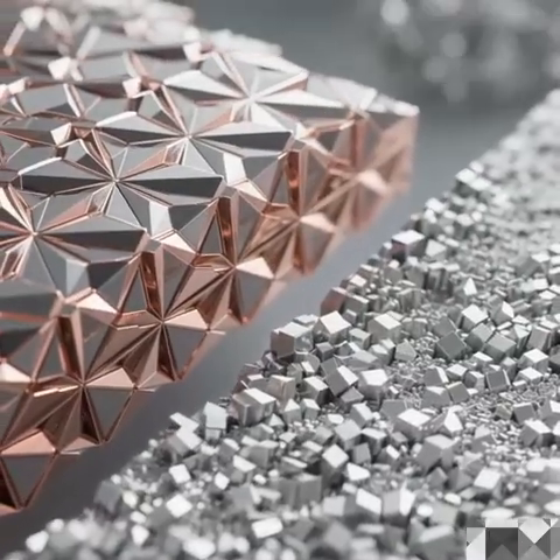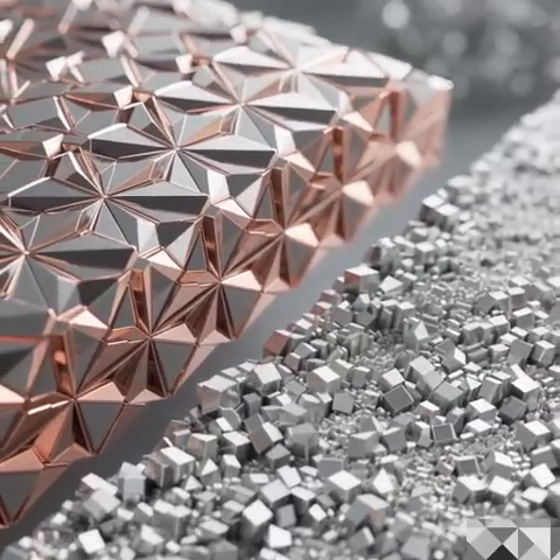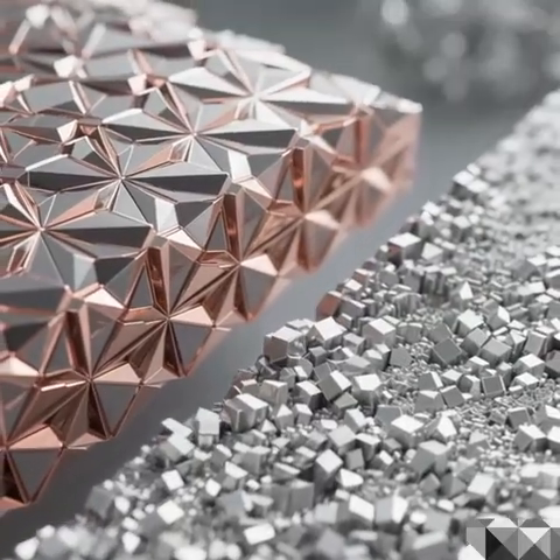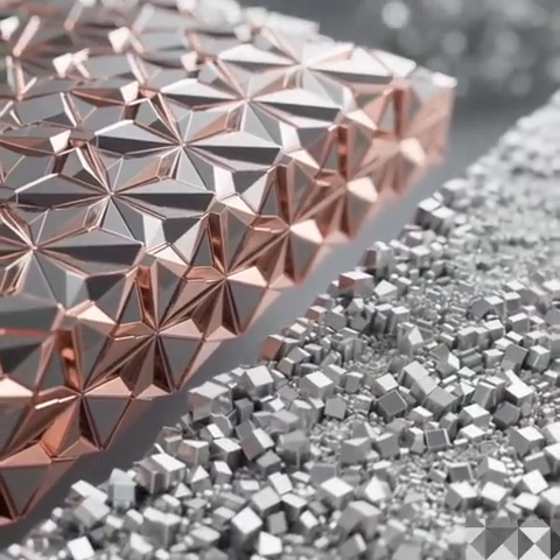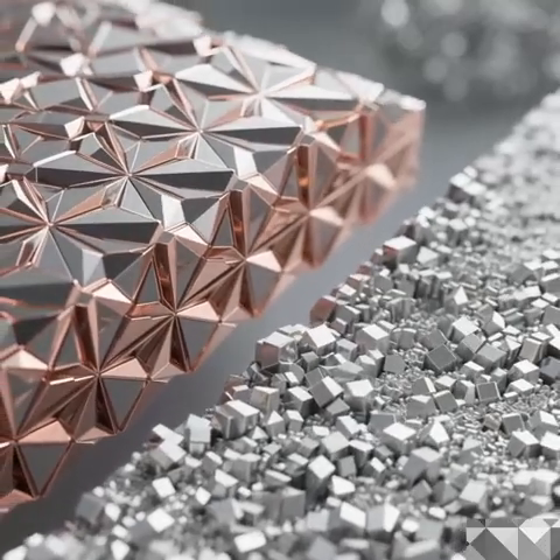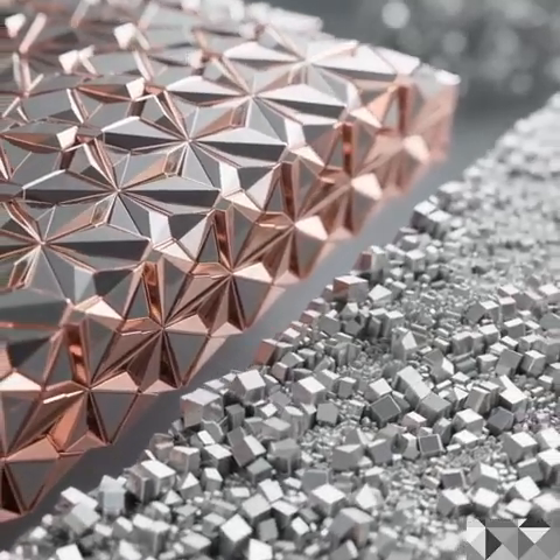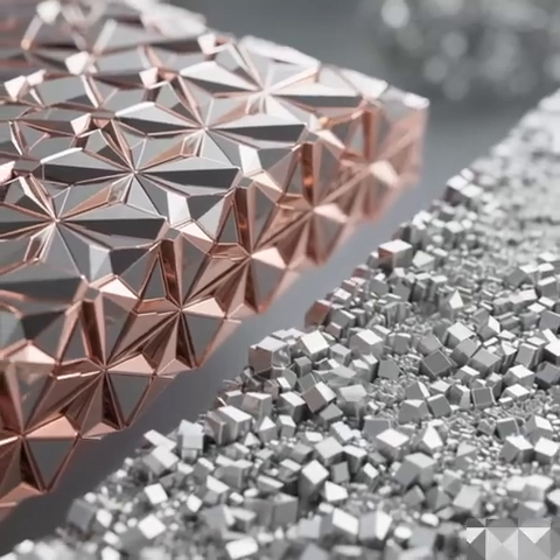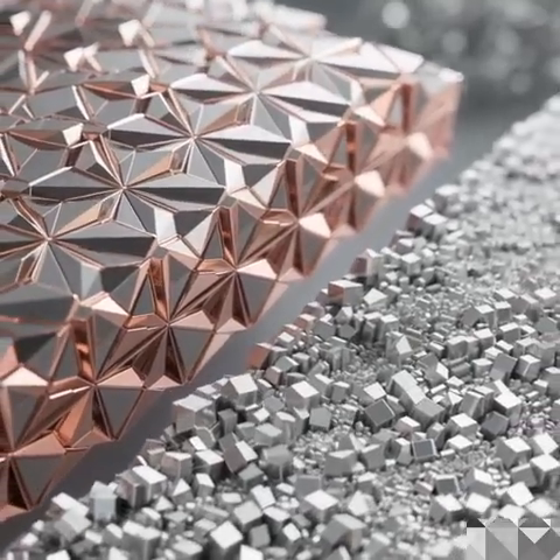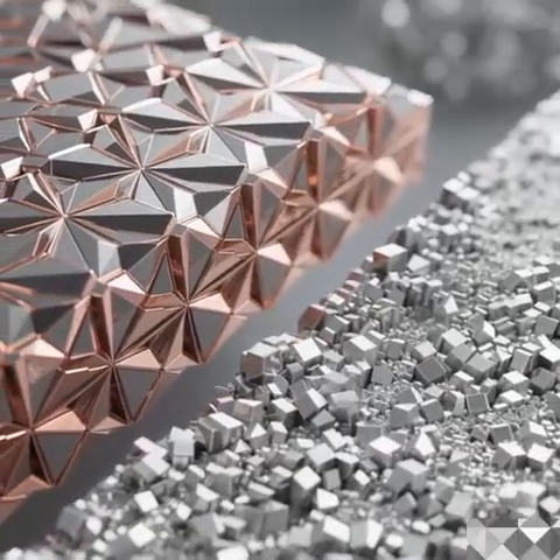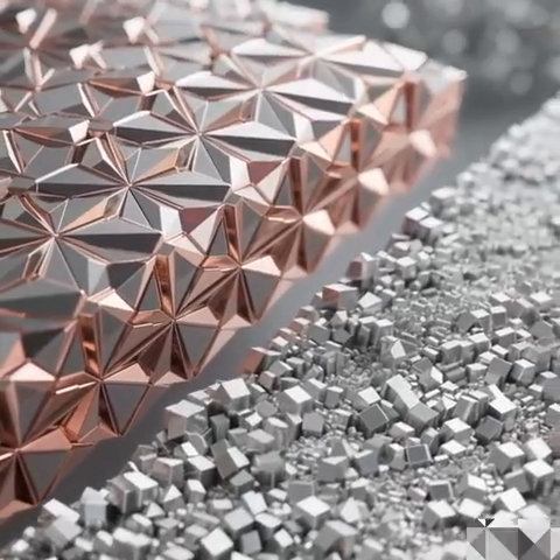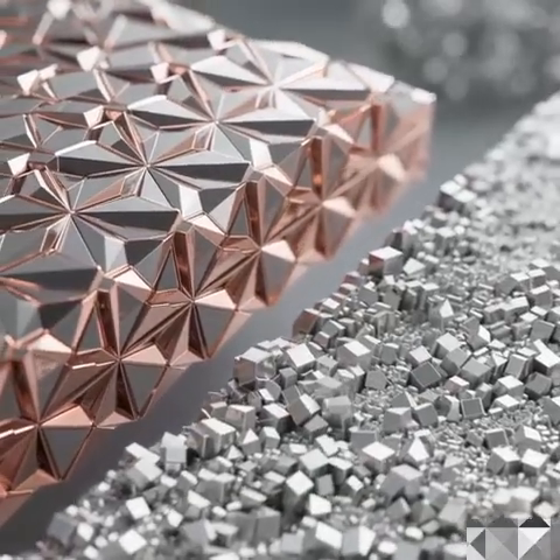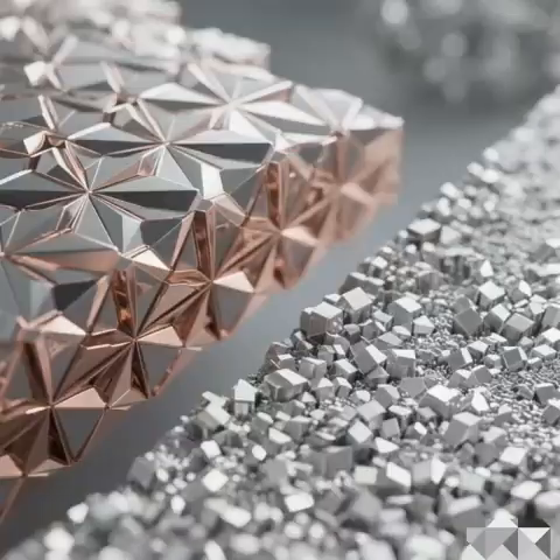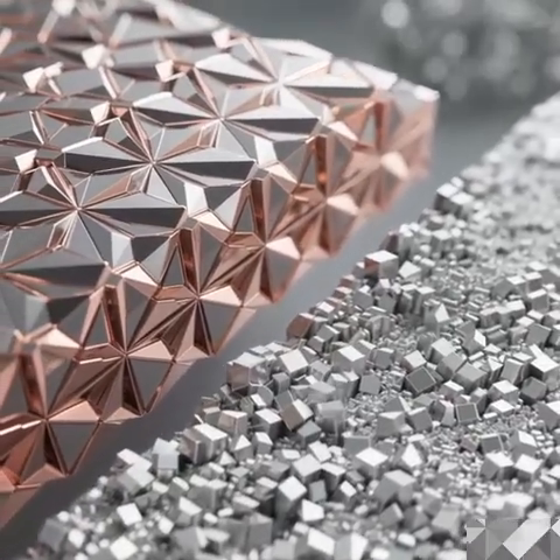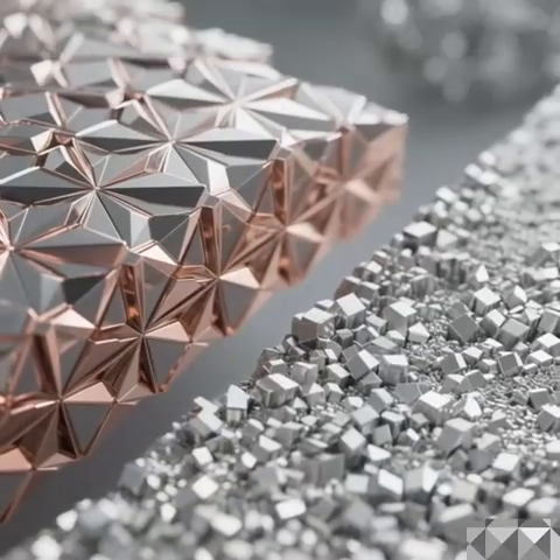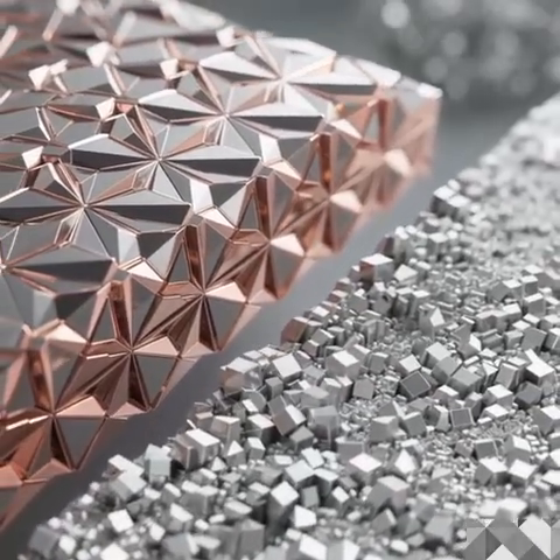Right. High-precision applications. Okay. Then the nanocrystalline copper, the NC plus CG system. The dual layer approach. Structure is that fine grain layer on top of a coarse grain layer. Correct. Diffusion is high through grain boundaries, but the big thing is the impurity management from that CG layer acting as a sink. Crucial for reliability. Bonding can be super low temp, 100 C for an hour, or faster at 200 C, like 5 minutes. Very flexible thermal budget. Surface treatment involves electroplating, focused on impurity control via that CG sink. It's excellent at stopping voids and impurities migrating. Making it very suitable for mass production. Right, really friendly for mass production, AI modules, high I/O density things.